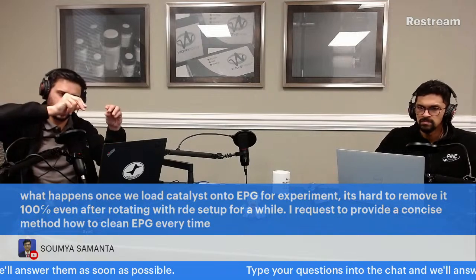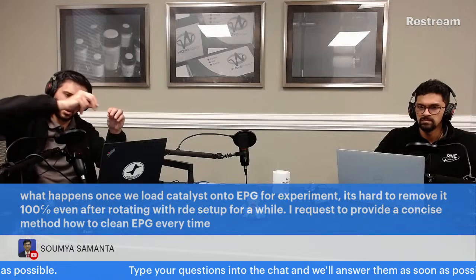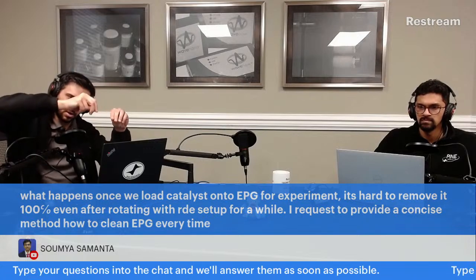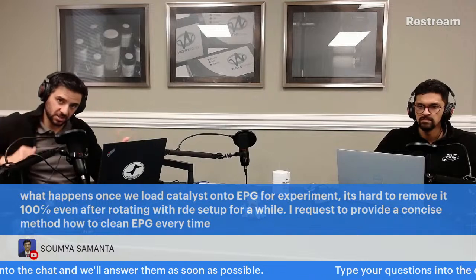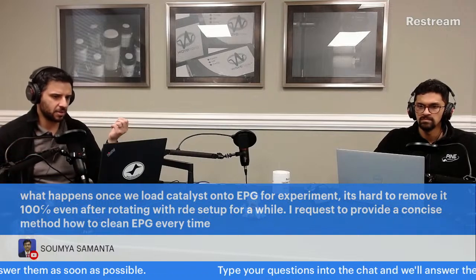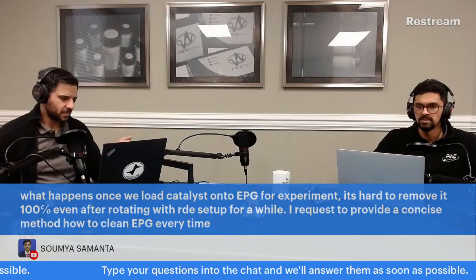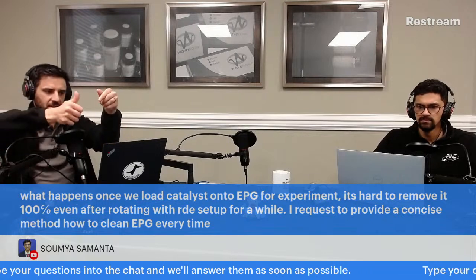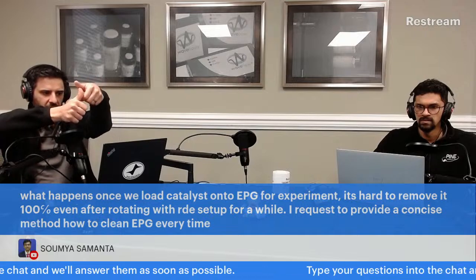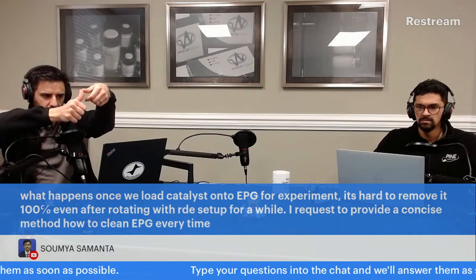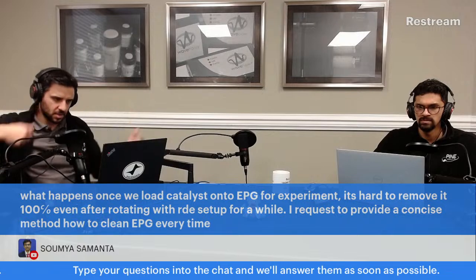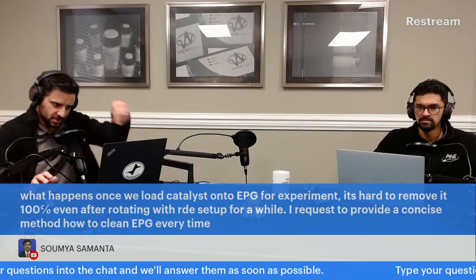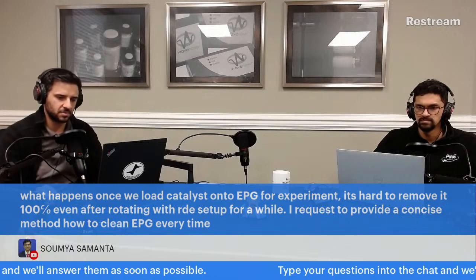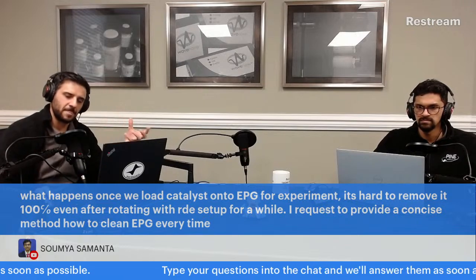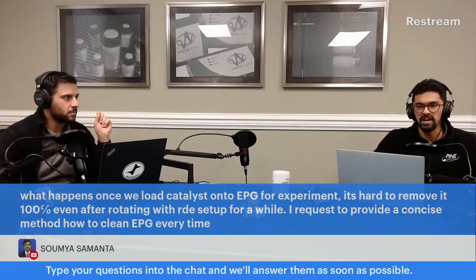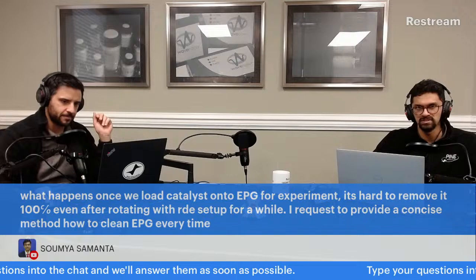Use a squirt bottle and spray it on. Don't touch the squirt bottle to the tip of the electrode surface, but spray it pretty hard so you can get the residue off. And then, like Alex said, like a microcloth or a Kim wipe, you can use your gloved finger. I'll try to demonstrate this. This is the electrode surface. You can use a gloved finger and very lightly press and dry it that way. Don't scrape and press. Don't use your fingernail. Don't indent the surface. But you can also use pure air and blow it off too. Air is another way you can dry it.